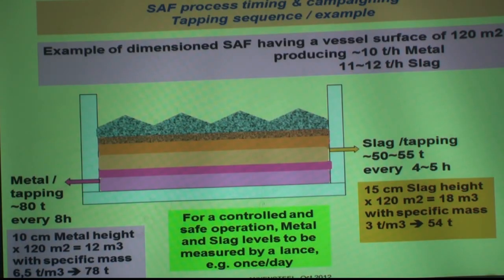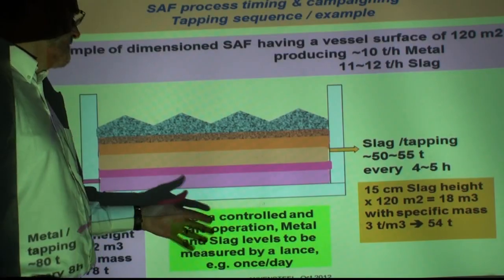So we can expect the slag height according to the temperature of the water cooling. That's one point. Yeah, that's right. But maybe not enough, because water cooling sometimes could be not enough. It is due to the wear. If you have more wear, even at one place, water temperature increases. So the solution is first to make an accurate mass balance of what you charge and of what you discharge, metal and slag. Okay, people did not do that. That's the first. And the second, I recommend to measure once a day metal height and slag height.